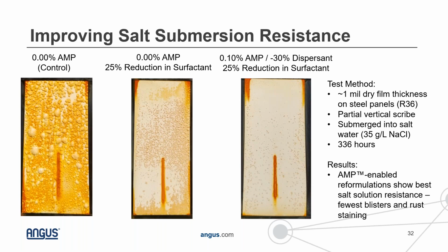This is showing results after 336 hours of salt submersion. So what you see on the control is that there's a lot of blistering and a lot of corrosion occurring. In the case of when we took the control formulation and reduced the surfactant by 25%, we start to see an improvement to this. But the best improvement was really seen when we took our reformulated formulation, where we used AMP as a co-dispersant, removed some of the dispersant, and also kept that surfactant concentration low. That really helped to improve the salt submersion resistance of this coating.